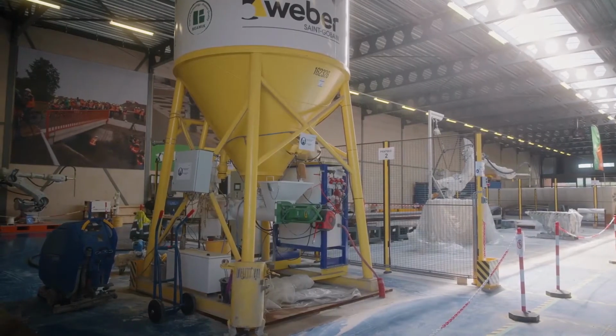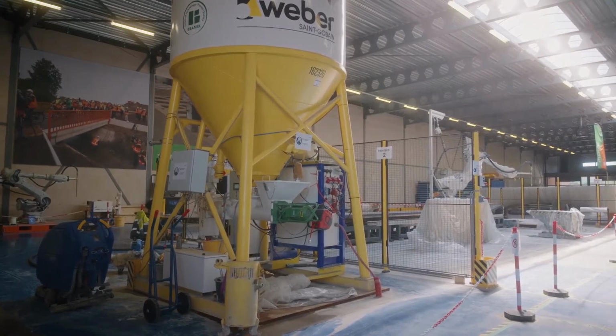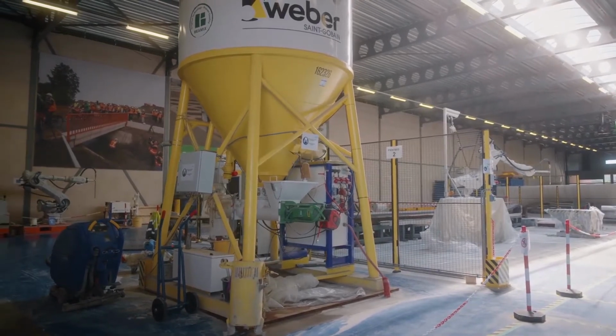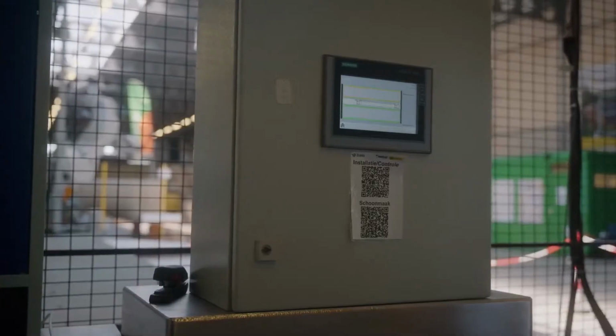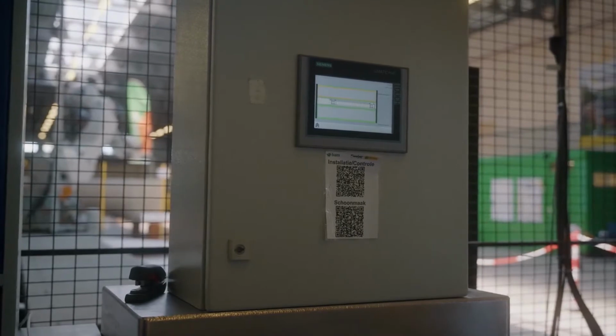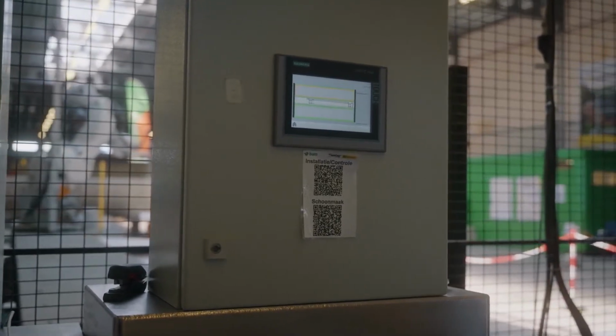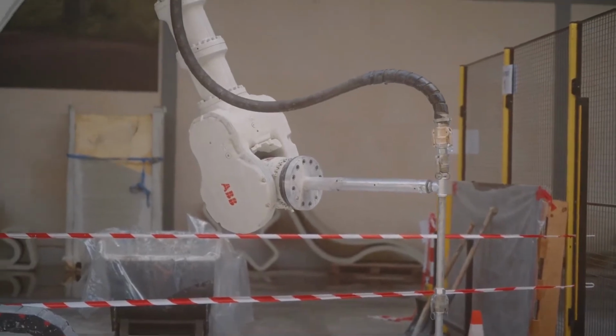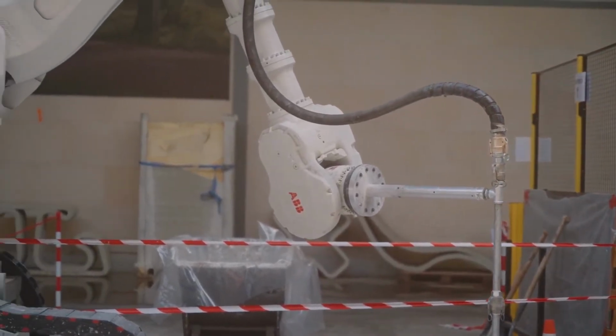We have a robust mortar, but also we need a robust system. So for the system, we have a silo mixing pump from MTech and SMP. We did modify the system a little bit. We changed the water dosing in order to have a more constant quality of the mortar that is being mixed and pumped. And we swapped the rotor stator in order to have a smaller amount being pumped as is being required by the robot. We have an ABB robot on a track,